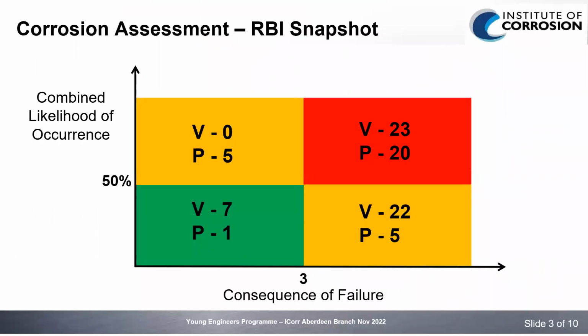So building on the integrity history that we were provided, we performed a risk-based assessment on the vessels and pipework, 52 vessels in total, and we broke up all the pipework into 31 corrosion circuits. We've done this so that we could then prioritise inspection going forward and identify the high-risk items. As you can see, we do have a bulk of them within the high risk section.